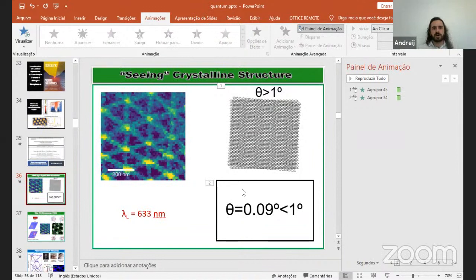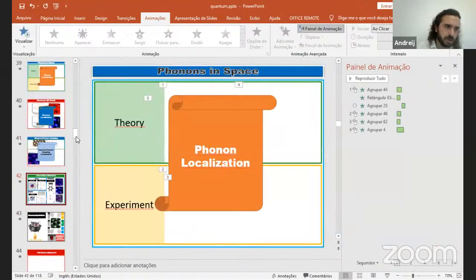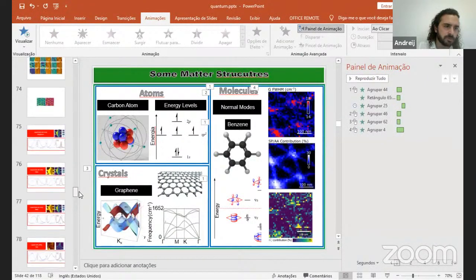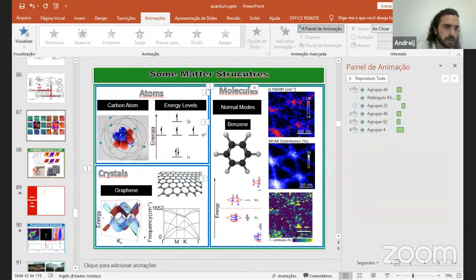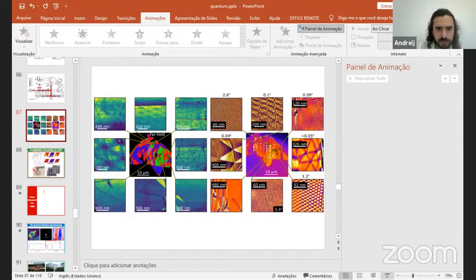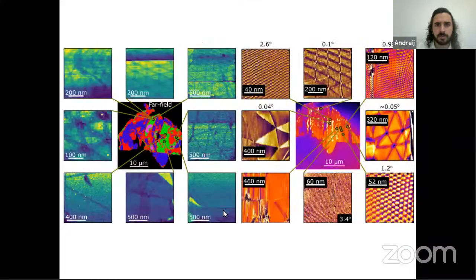You mean this kind of work is for twisted bilayer graphene or for other structures? Yeah, it's for tiny angle twisted bilayer graphene. We didn't see this. We only saw triangular geometries below 1 degree. But for angles larger than 1 degree, we saw some nice results on s-SNOM, which is another alternative technique, in collaboration with Gilberto. So we saw very different structures here. This is some example. Can you see? Yep. So we saw very different structures above the reconstruction, but below the reconstruction, we only saw triangular geometries.